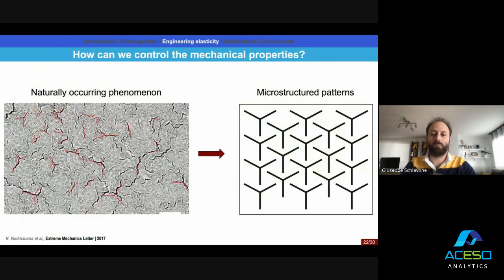So what we did with the gold was actually tune the fabrication process so that this actually happens naturally in the gold. In other words, we have a machine that deposits gold on the rubber. If we tune in some certain way the conditions of this deposition, then the gold grows or is deposited with this microscopic structure. But gold is not really a good material for medical devices because it tends to dissolve and corrode in the body. So we wanted to have the same approach, but with other materials.